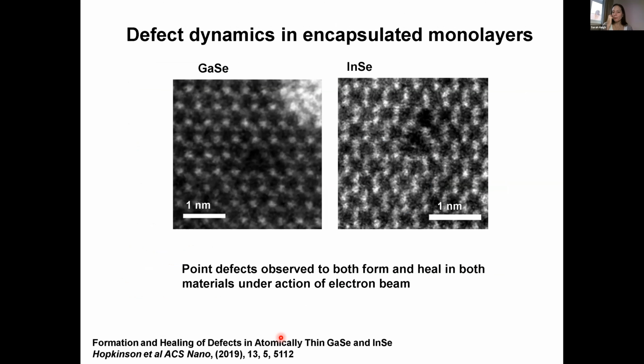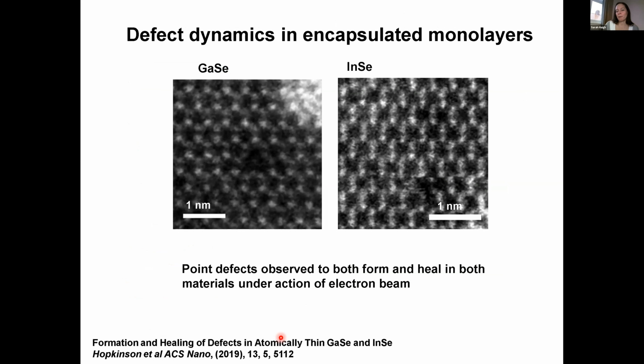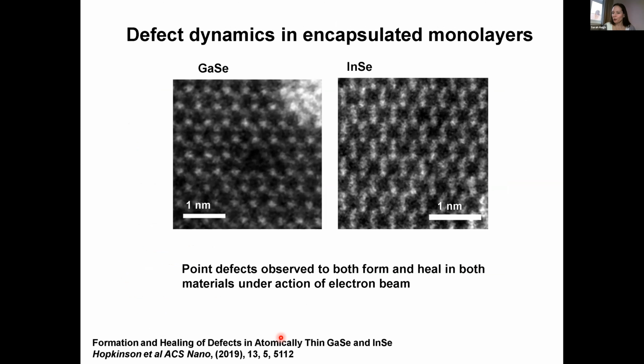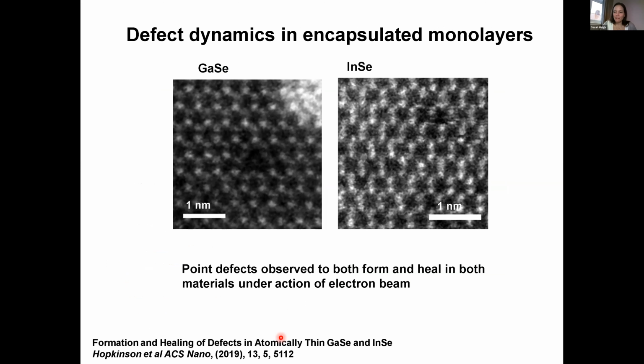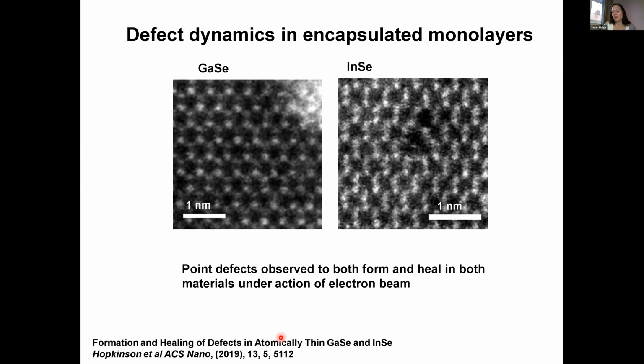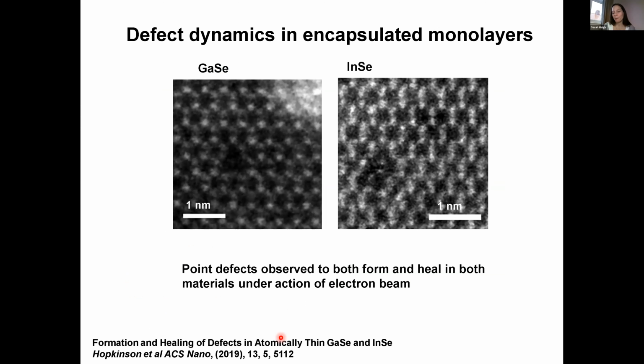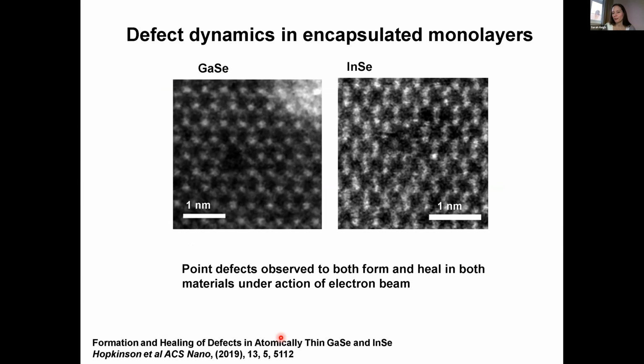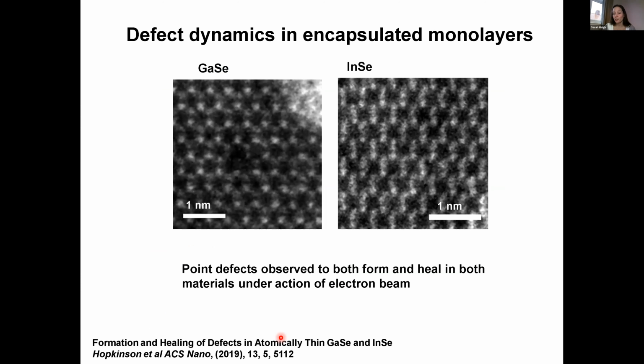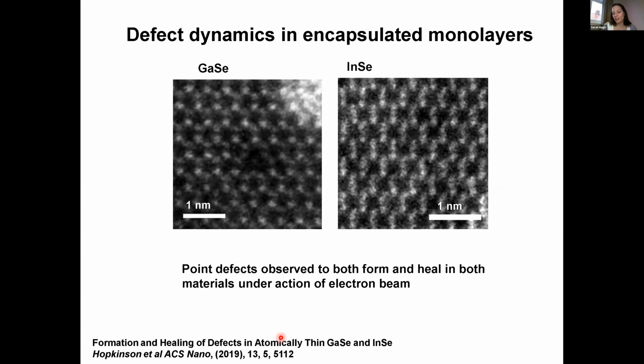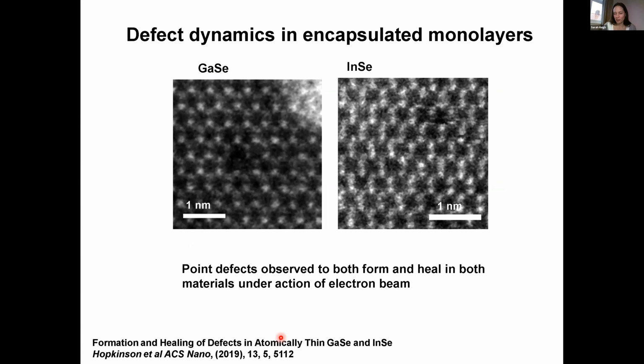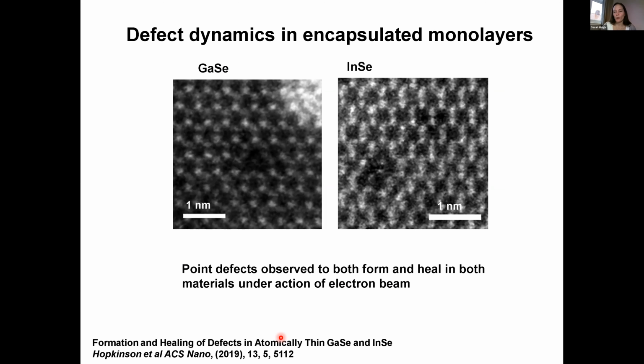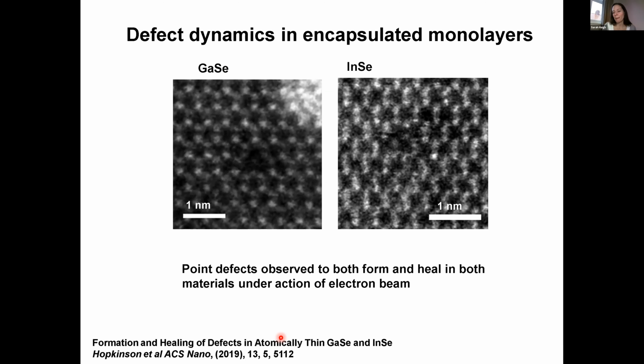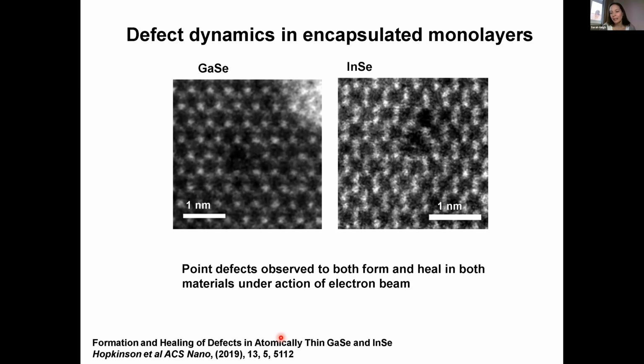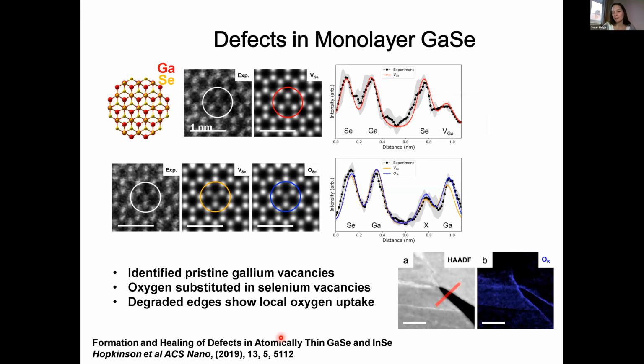However, here we can just look at the post-transition metal chalcogenides. These do have defects in them. We are producing defects with the electron beam, even when we use low energy, especially when we've trapped contamination between our two graphene sheets. We see a huge increase in the amount of structural degradation that we get in these materials when we have oxygen vacancies or water trapped under the graphene. We can characterize what we're getting for these types of defects.